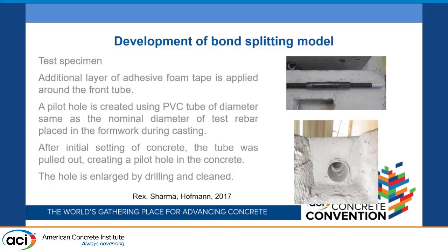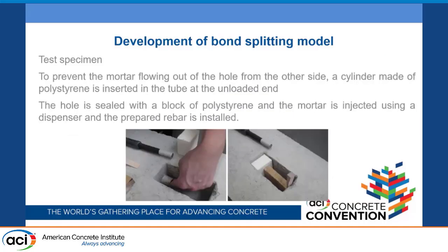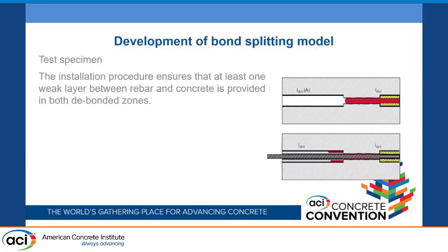When we did all of these things, we could get a clear pilot hole, the bigger hole to avoid the bonding in this region. We had the clear zone where we have the full bond and the clear zone where we do not have any bond. All these things are available in the literature, in the paper, so I will not go so much into details, but we took every measure to make sure that we have clear bonded and debonded lengths. And eventually the idea was that no matter where we are, in the front or in the back, in the debonded region, we have at least one weak plane, which allows us to have a free movement without any bond coming into picture. So that way we had clear bond lengths and debonded zones.